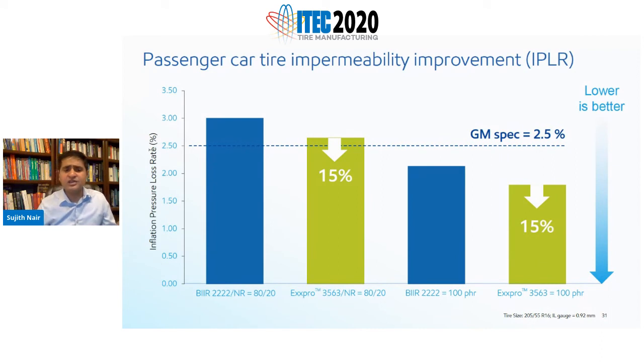And then finally, this is the inflation pressure loss rate results of bromobutyl and Exxpro in two different formulations. If you look at the first bar, it's a bromobutyl natural rubber formulation 80-20, which is standard in the industry. If you use Exxpro instead of bromobutyl 80-20, you get like 15-20% improvement in your IPLR. Similarly, if you compare Exxpro 100 PHR to the bromobutyl 100 PHR, you again see this 15-20% improvement in the IPLR of tires utilizing Exxpro.